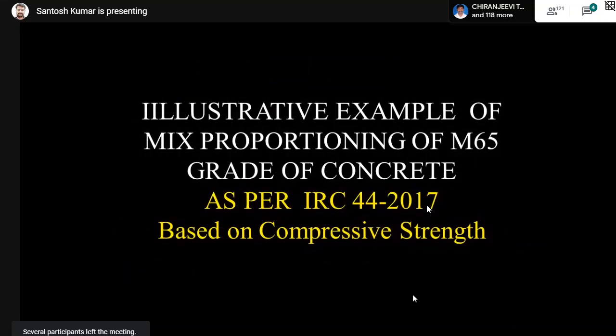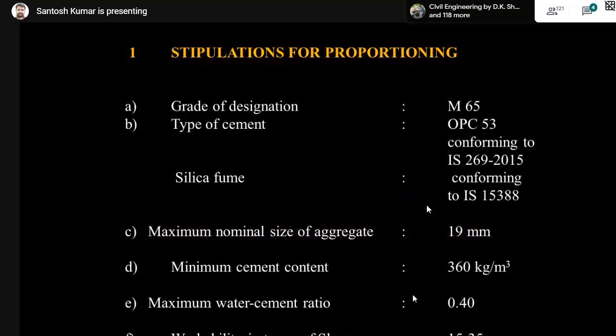So there is an example of concrete mix design of M65 grade based on compressive strength. I just wanted to tell you how it is being calculated. The grade of concrete designation is M65. Cement we are using is OPC 53, conforming to IS 269. Silica fume we are using conforms to IS 15388. And the nominal size of aggregate is taken as 19 mm.